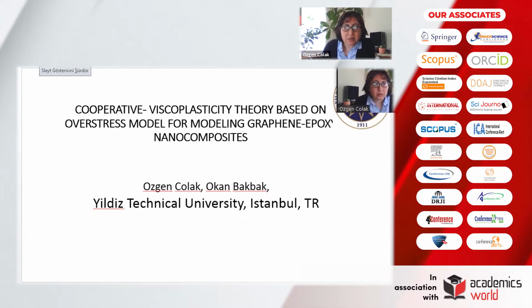As you can see, we start with functionalized graphene. We add epoxy resin, and in the magnetic stirrer, it is stirred 15 minutes. Then using the 3-roll milling, we mix it, and then hardener is added. Again, magnetic stirrer is used. It is molded and cured at 80 centigrade degrees for 1 hour, and then 160 degrees for 4 hours, and we get the specimen. And this is the procedure that we follow in the manufacturing of nanocomposite specimen.